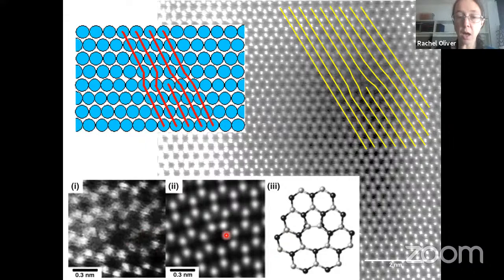This is just the same type of image, but now with a very, very detailed look at the atoms around the dislocation core and a simulation here of that slightly noisy transmission electron microscopy image, which is based on a structure here, kind of a ball and stick atomic model, if you like, of the dislocation. And we can now see that there's different numbers of bonds around the atoms in the normal crystal compared to the atoms in this crystal. We're no longer forming these 6-membered rings, but instead the bonding has been distorted to form here a 5-membered ring and here a 7-membered ring. So a different bonding structure and a real disruption in the periodicity of the crystal.